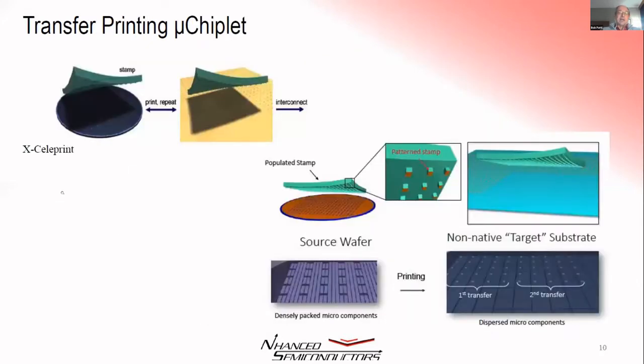Another promising technology is transfer printing. Transfer printing uses an elastomer to pick up dielets that can be extremely small. Small is 25 microns on the side, perhaps smaller. NHanced is currently working on a program where we're transfer printing buffers onto a passive interposer, and those buffers are on the order of about 40 microns on a side. With the elastomer, you can pick up arrays of these devices, transfer, print them from a source wafer onto a